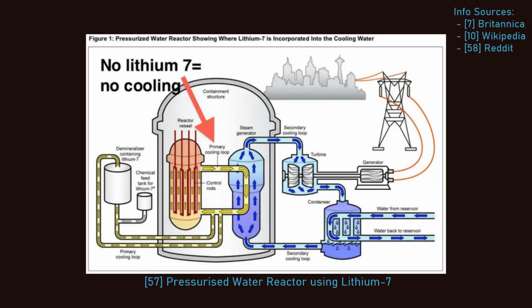However, weapons are not the only use for lithium in the realm of nuclear physics. The element is also used in nuclear reactors as an anti-corrosive agent. In pressurized water reactors, the pH of the coolant is kept high to minimize the pitting and corrosion of the metals used in the hydraulic system. For this reason, lithium-7 hydroxide monohydrate is often used as an alkalizing additive to reactor coolants. Lithium-7 is used because it has a low nuclear cross-section, which means that it is less likely to absorb neutrons coming out of a reactor core, which would then cause the isotope to decay into tritium.